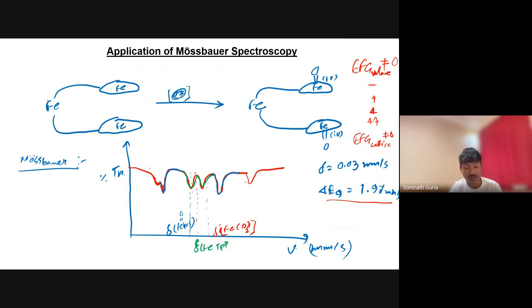So this iron 4 system can be monitored by the Mossbauer line, but the Mossbauer spectra shift towards the more negative direction, starting from 0.03 millimeter per second for the iron TPP iron 3 center, after oxidation and generation of the iron 4 oxo species. This delta value shifts in a more negative direction.